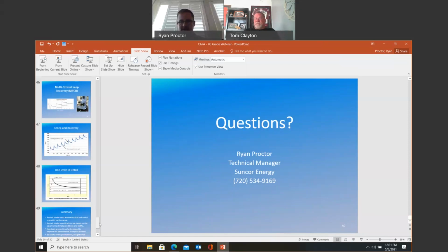Warm mix additives, and I would bet everybody who touches our industry at some point has heard about these. There are a variety of different options. Again, they're supplier specific. Speaking for Suncor, we have chemicals that we can add to the asphalt binder, and the entire point of it is, to use your example earlier, if it's 35 degrees out, instead of going to 350, you could keep it at 300, put this material in there, and it would behave more like it would if it was at 350.